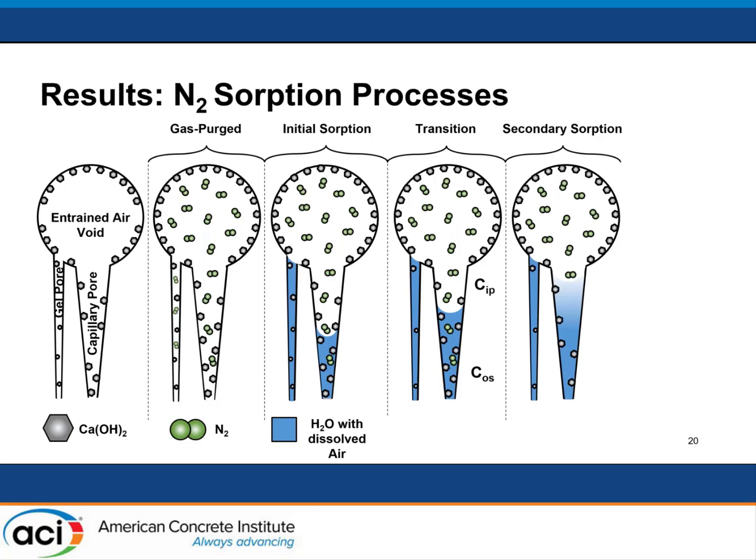similar. So the basic takeaway there is, had we pre-saturated the water with CO2 in the CO2 filled system, it probably would have behaved more similar to the nitrogen filled sample. In the same case for methane, if the water had been pre-saturated with methane, the dissolution process could not occur at the same rate.